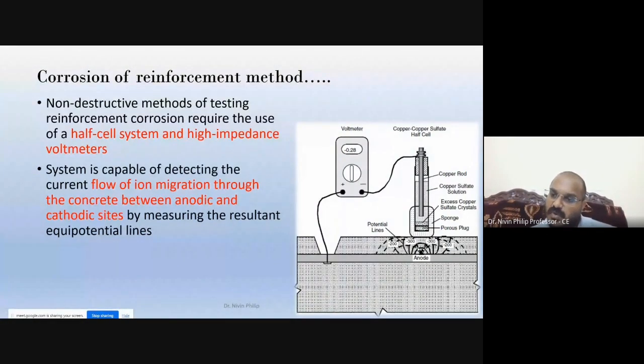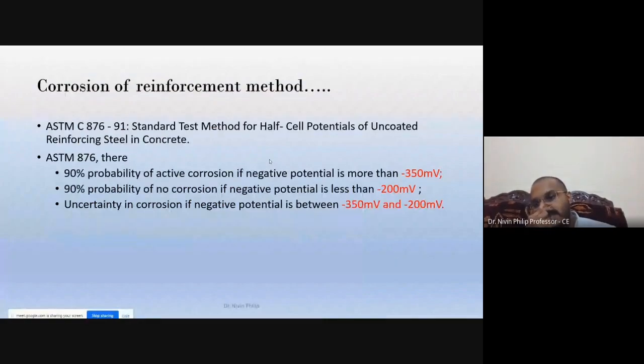Also, the current flows through this half cell to the rebar, and then it is connected to the voltmeter. This is the way we make a half cell. One disadvantage is that the half cell will give the value in only two stages: whether our rebar has 90% corrosion or 90% is good with no corrosion. That is, if the voltmeter reads minus 350 mV, there is a 90% probability of active corrosion.